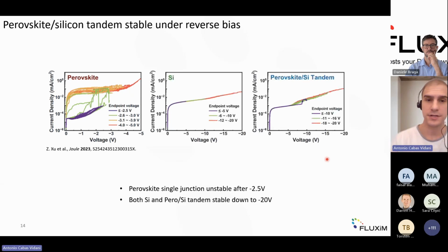But if you combine the perovskite together with silicon, now here we're talking of silicon-perovskite monolithic tandem, then we see that silicon is actually getting most of the reverse bias, and so the overall device is almost as stable as the silicon instead of the perovskite. So this is also an alternative way for commercialization of perovskite, and it looks indeed rather promising in this direction.